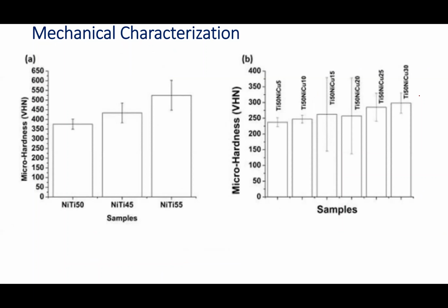Okay, as far as the material characterization is concerned, the samples of these laser additive manufactured structures were cut transverse to the direction of the laying and prepared using a standard metallographic technique, and a microhardness measurement was carried out at an incremental distance of 25 micrometer at a load of 500 gram. In this case, the average microhardness of the NiTi structures is in the range of 380, 440, and 525 HV. The microhardness is higher for a titanium-rich sample, and this might be due to the formation of a hard phase caused by the increase in titanium content.